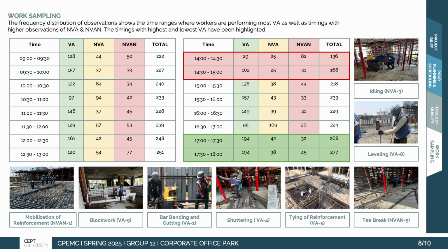The table shows the observations of labor counts for each tour that happened every 30 minutes. So for example, from 9 to 9:30, we observed 128 laborers performing value adding activities, 44 performing non-value adding activities, and 50 performing non-value adding but necessary activities. And the frequency distribution of observation shows the time ranges where workers were performing most value adding as well as the least value adding.